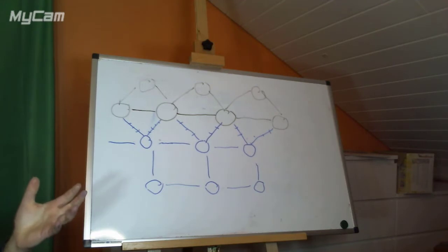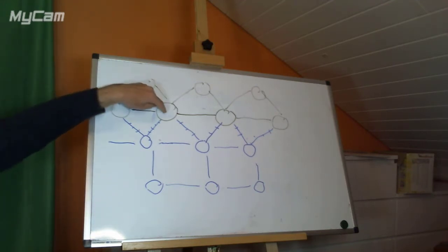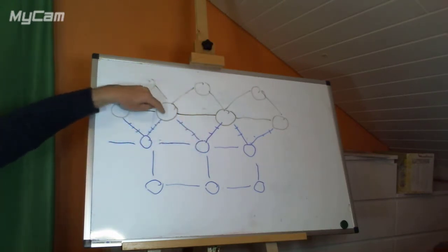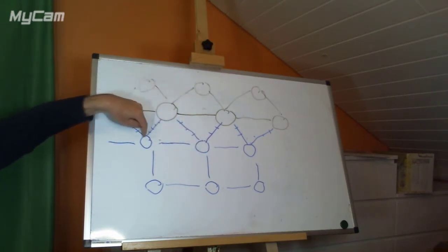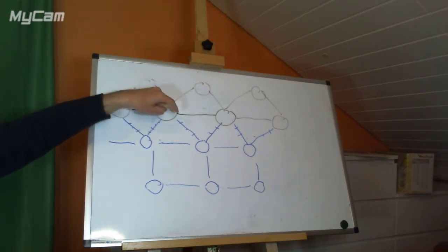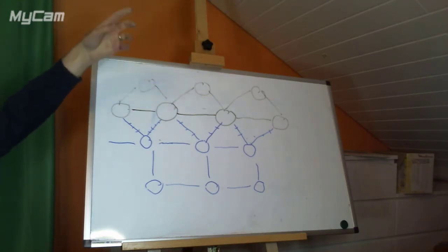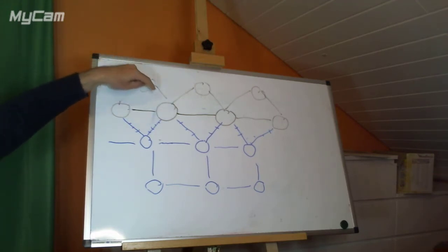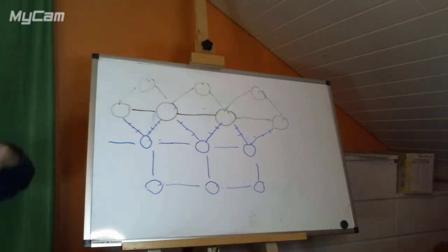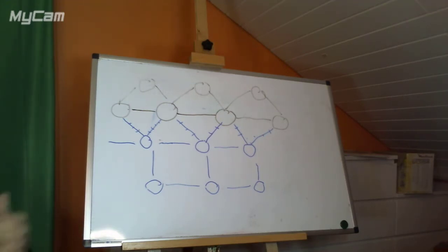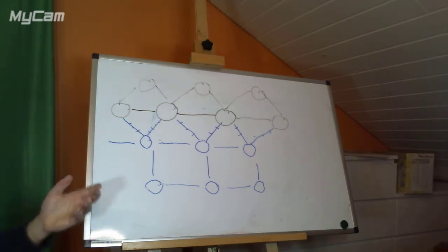But that is extremely unlikely to happen. Why should the bond length of this be some kind of multiple of the one below, and the number of bonds exactly match? So in this case I've allowed them to have 2 half bonds to each other, and that will allow it to be satisfied, although I have avoided the problem that the black ones would have broken 2 bonds and the blue ones would have only broken 1, so the number of electrons will also not add up. So we'll always end up with a problem unless we have extremely well matched materials.